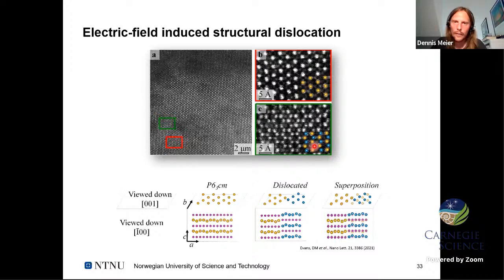But then in the dislocated structures, we get these double structures. And that's exactly what you would expect when we have the superposition, the dislocated structure here. So that convinced us that we really have induced the partial dislocation with an electric field.